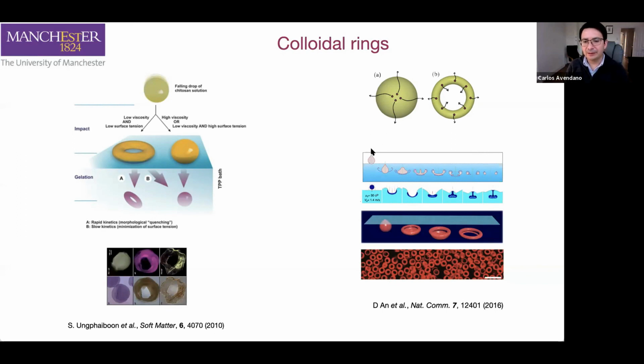So what they have is some droplets of nanoclays. It's something that as soon as you create a shock or a small perturbation in the system, they will form a gel. So they have these nanoclays in suspension, and then they let this droplet fall on a surface. When you let a droplet fall on a surface, it will tend to form some sort of toroidal shape. This is something that you can observe from fluid mechanics. If you do CFD calculations, you can obtain that kind of shape. So what they decided to do is, maybe in that droplet, we can include these nanoclays. And depending on the speed at which they are falling, they will be trapped in different stages. And they optimized the speed of that droplet to try to get these rings.